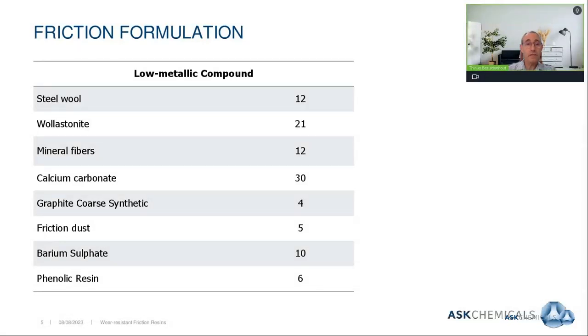In this comparative study, we have chosen a low metallic friction compound based on steel wool and mineral fibers. In this case, we have chosen a functional filler like wollastonite. Of course, calcium carbonate as a non-expensive filler, graphite and friction dust to balance the lubricant effect, barytes or barium sulfate as a heat-resistant filler, and lastly, the phenolic resin itself. You will note that the phenolic resin has already been optimized to a 6% level, which in the friction industry may be regarded as a well-optimized level.